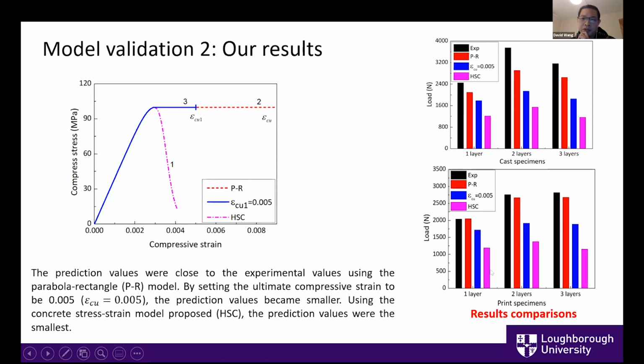If we use the real unconfined stress strain curve for high strength concrete, the prediction accuracy is much less. Also from these two figures, we can see that in general, the prediction accuracy is higher for the printed samples. But we cannot say that this numerical procedure works well for the printed samples, because we have only a quite limited number of samples in our case.